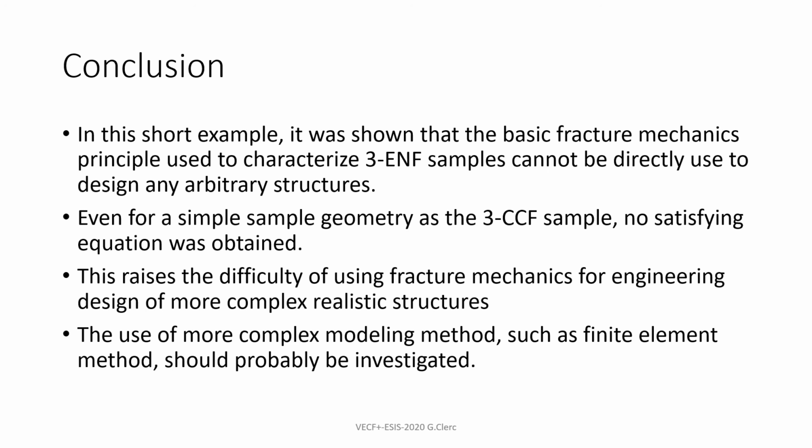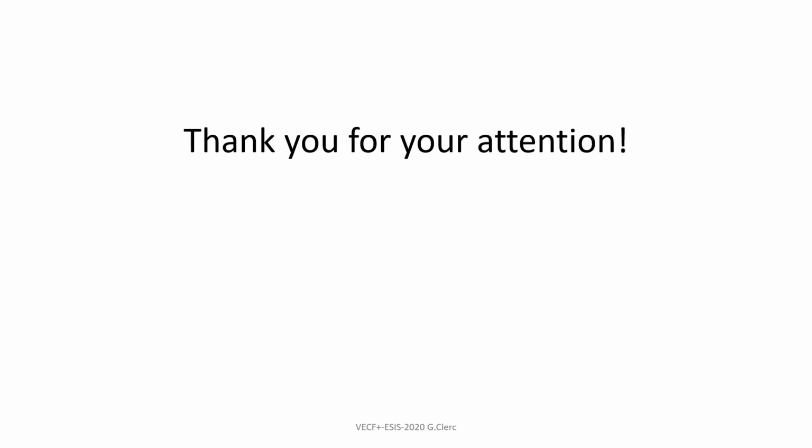So in conclusion, in this short example, I wanted to show that the basic fracture mechanics principle used to characterize 3ENF samples cannot be directly used to design arbitrary structures. Even for a simple geometry such as a 3CCF sample, no satisfying equation was obtained. This raises the difficulty of using fracture mechanics for engineering design of more complex realistic structures. And probably the use of a more complex modeling method such as the finite element method could be investigated. With this, I'm at the end of this presentation, so thank you for your attention.